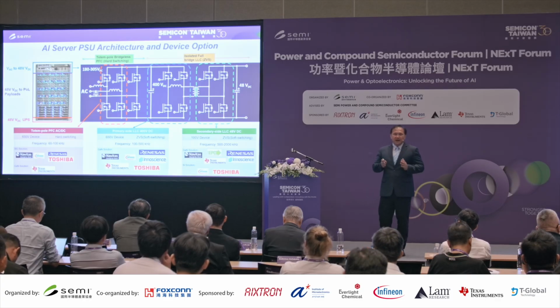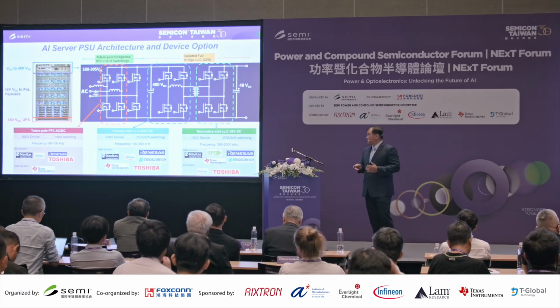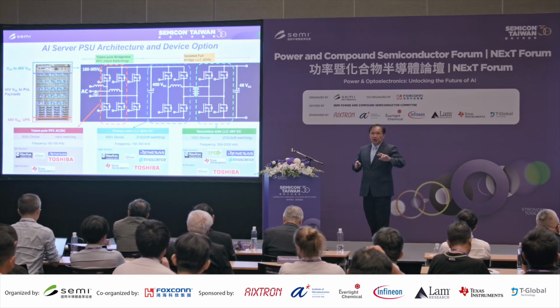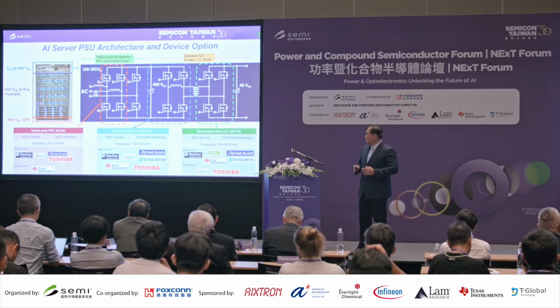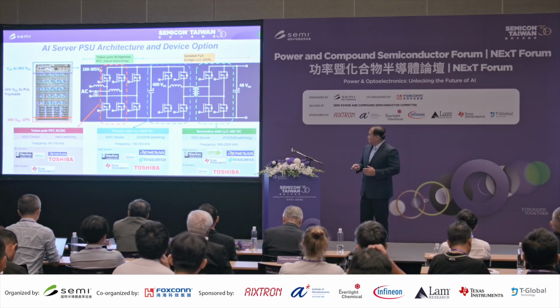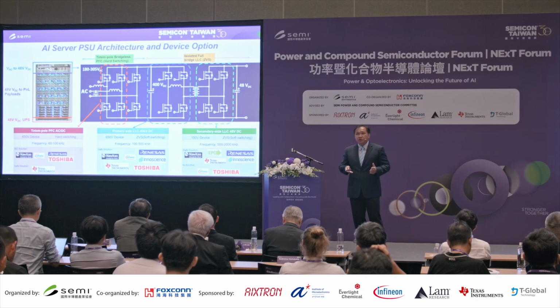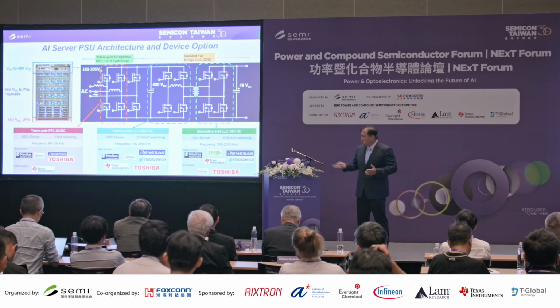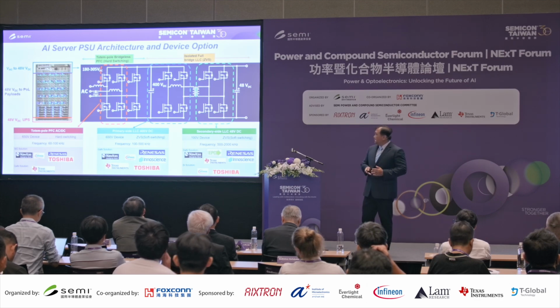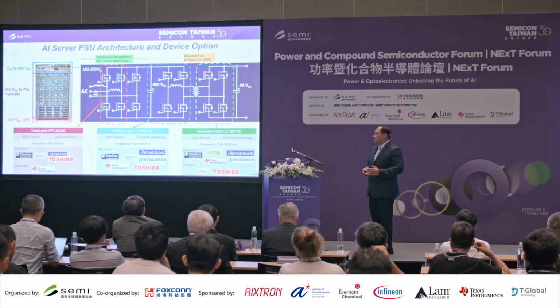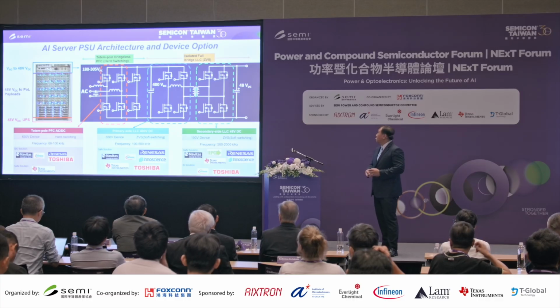Just because for GaN on silicon, you still have to face the high temperature. The Ron has performance degradation at high temperature, even more than twice in magnitude. So it's very important for PFC, especially at high temperature. You have to face the hot carrier effect. So for 650 volt gallium nitride, especially for hard switching, it's still challenging.